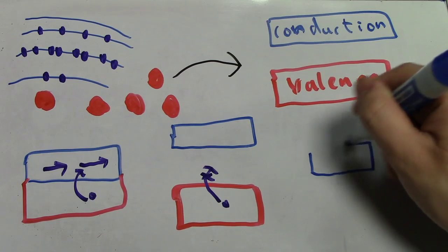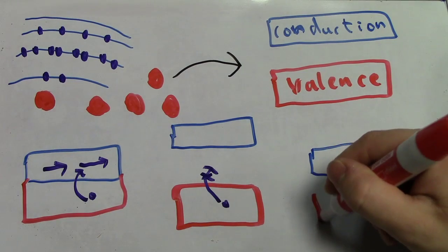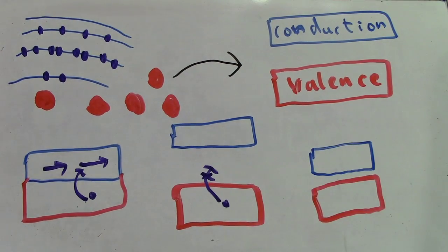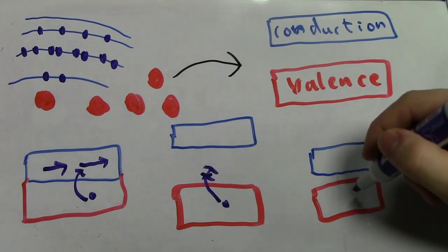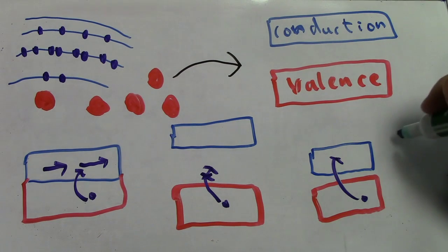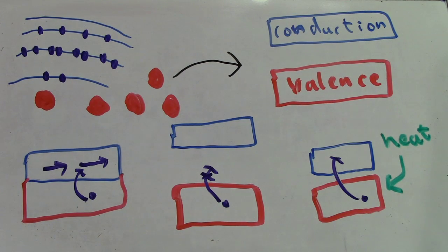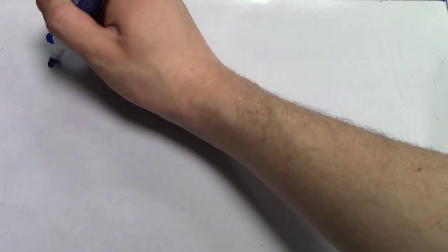Semiconductors, then, are in the middle. They still have a band gap, but only a small one. So electrons require only a small amount of energy to jump into the conduction band and begin flowing. Sometimes this energy can be provided by thermal energy in the solid that randomly excites some electrons into the conduction band. So, in other words, semiconductors sort of conduct. In general, thermal energy is a very poor way to increase the conductivity of a semiconductor. Luckily, there are ways to reduce the size of the band gap.